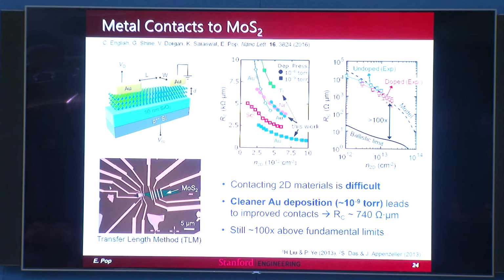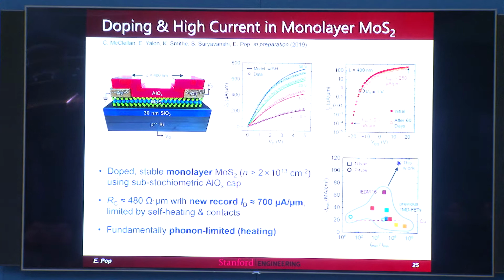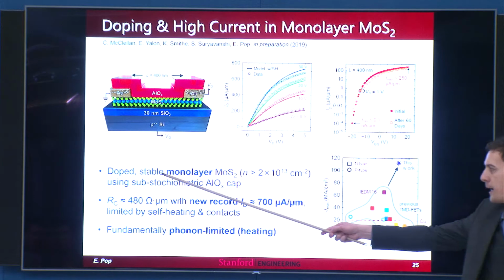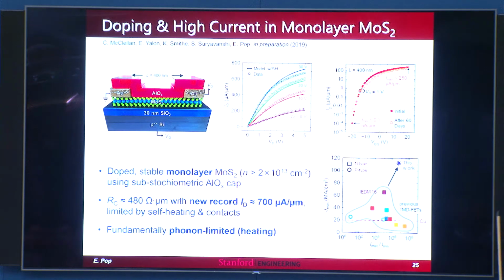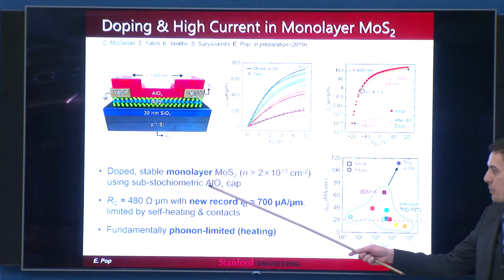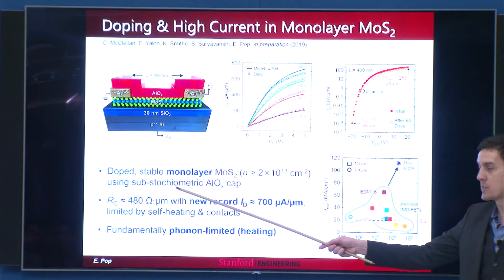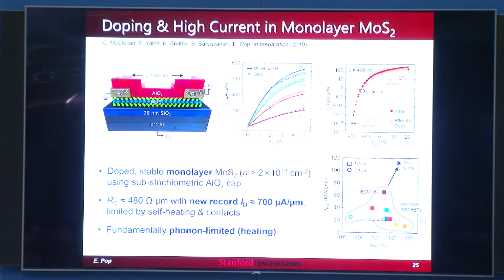So we know we can still improve this quite a bit. I mentioned doping. There's two ways we do doping in our group, and we were very interested in making stable dopants. It's possible to dope these things with liquid dopants or gel-like dopants, but they're not 3D integration compatible. And so one simple way to dope these things is to pretty much put aluminum oxide on top of them. And if it's substoichiometric, the aluminum oxide is essentially charge transferring to the MoS2, and it's doping it N-type, and it's a very, very stable capping doping layer.